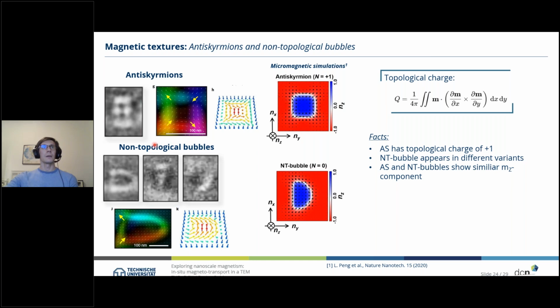And then we have the so-called non-topological bubbles, which are shown here in LTEM images on the bottom, a bit more blurry. They show up in different directions. That's why we have different types, either showing to the right, to the bottom, to the left. But they all have this magnetic configuration, which is this half elliptical shape.